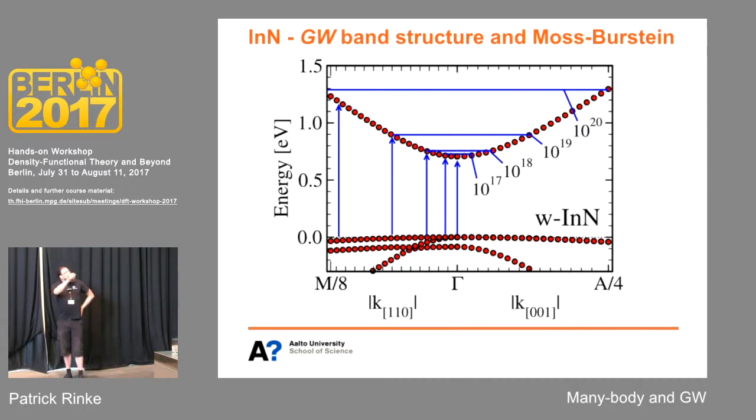And then here you can work out basically up to which energy this band is filled, given the curvature of the band and the electron concentration. You can see you start filling it up very quickly as a function of carrier concentration. Now the way the band gaps were measured was by optical absorption, right? So you make an excitation here at the gamma point, and that's how you would determine what the band gap is. But you cannot make this excitation if electrons are sitting there. That state is just simply not available.